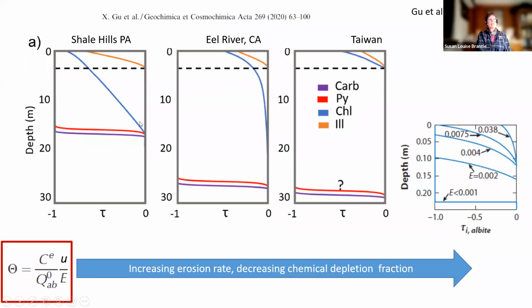On the other hand, if you look at the chlorite, which I told you at Shale Hills was not a fast enough reactor that it disappeared, but it actually was being exhumed at the surface, you can see that you're moving towards less and less weathering of that chlorite. So you're sort of moving in this direction in these systems. So this experiment really, I think, tells us that these models, even though this is albite plus quartz and these are shales, these models are telling us something really powerful about how these systems operate.